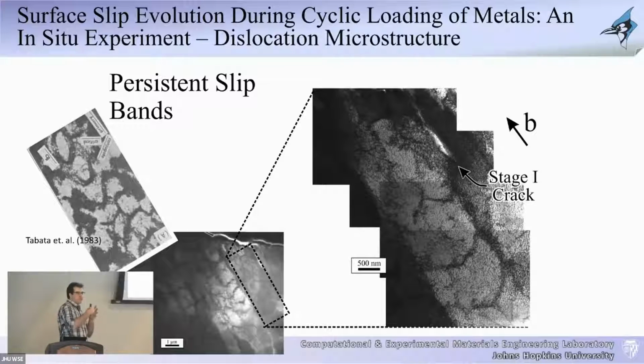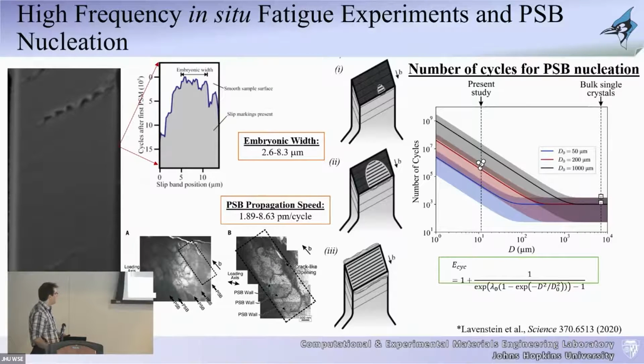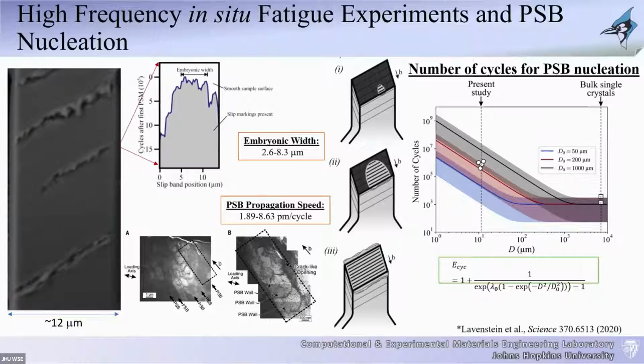So what we're showing with these types of experiments is that, yes, there are size effects. We are going down in the scales. The life of the component actually is prolonged. But nevertheless, the types of mechanisms that form, the types of structures that form, the types of defects that form are exactly similar and mimic what you see in a bulk experiment. And thus, this allows us an opportunity to do these types of experiments to understand how deformation and failure happen.